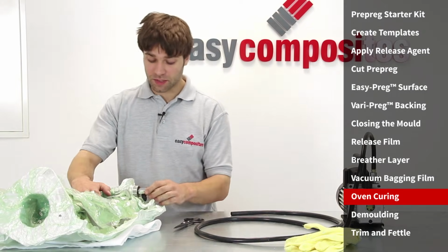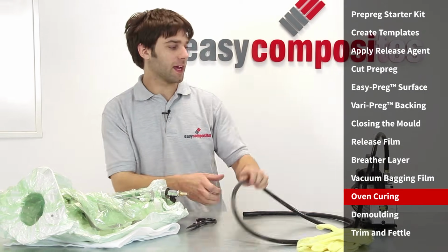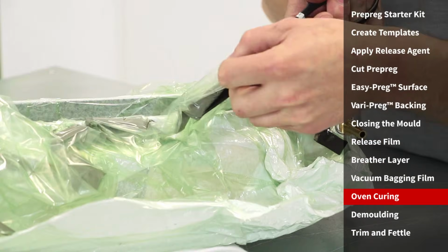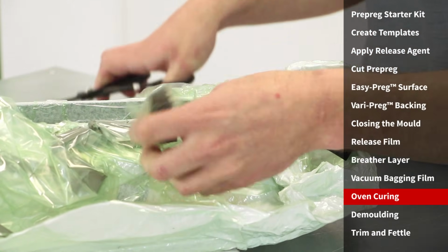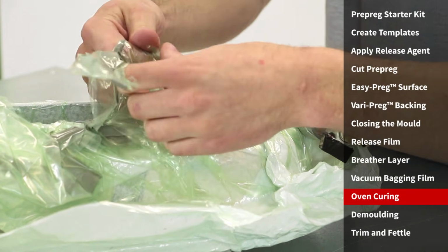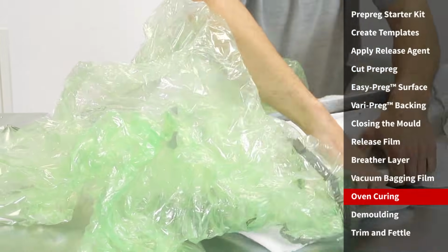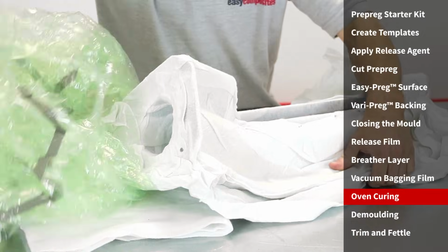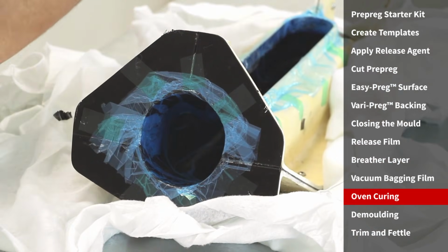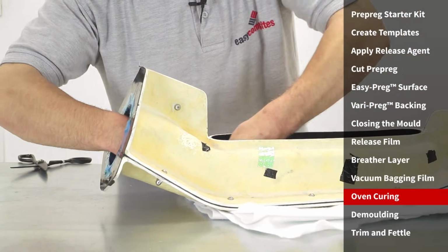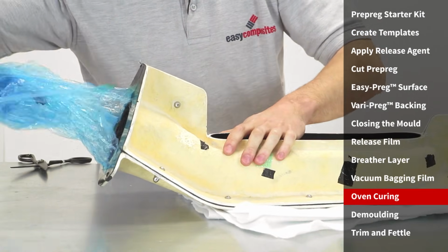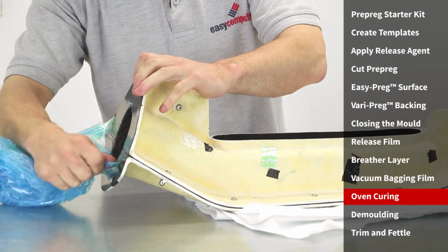We're back down to room temperature now, so we can look at removing the bag. Like most vacuum bagging processes, we generally regard the vacuum bag as disposable, but don't forget to remove the through bag connector first. Breather cloth can, if you like, be saved and used repeatedly, but like the bagging film, the release film is normally discarded.